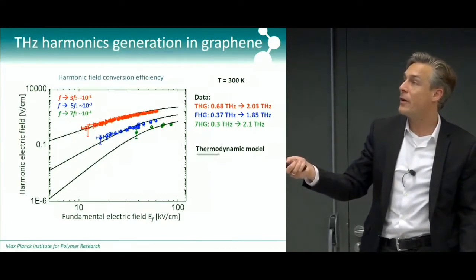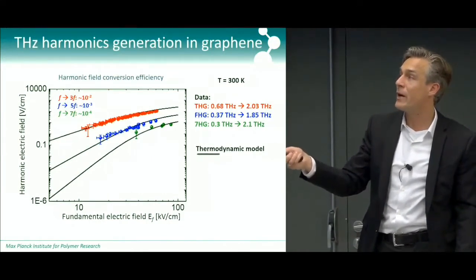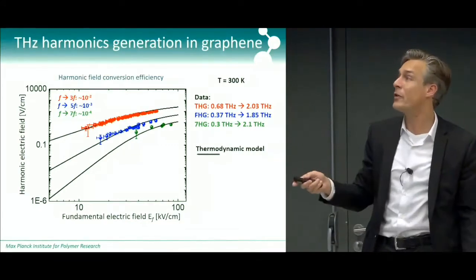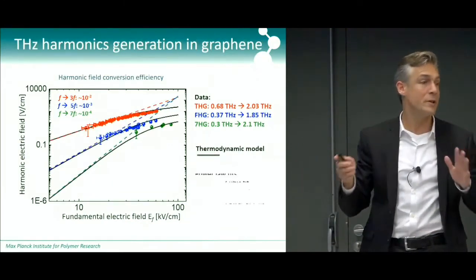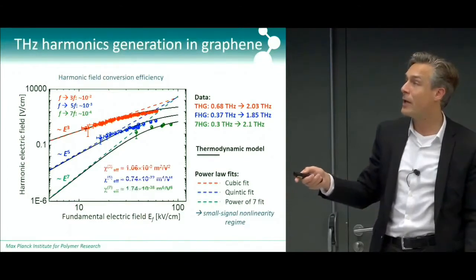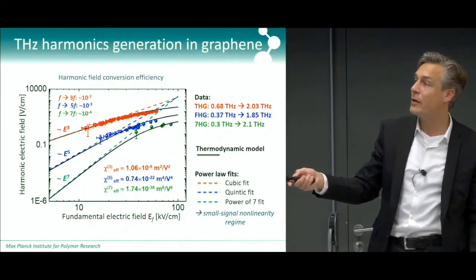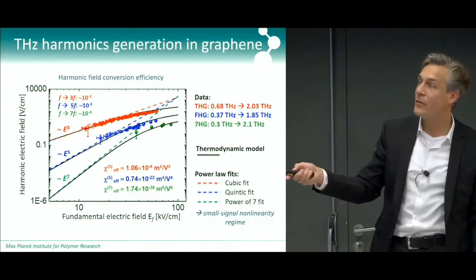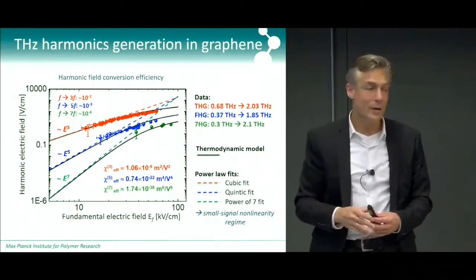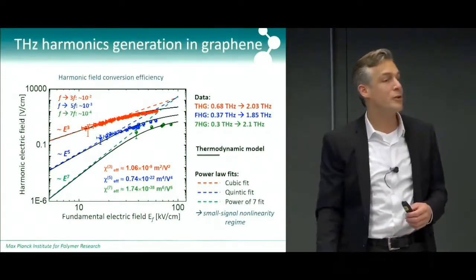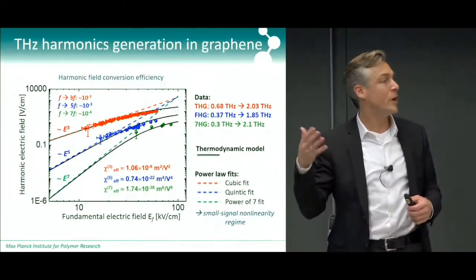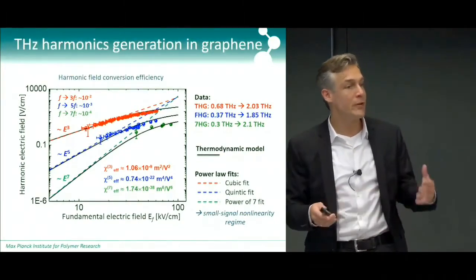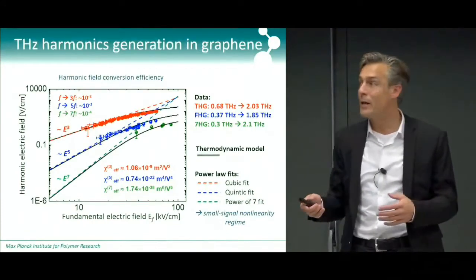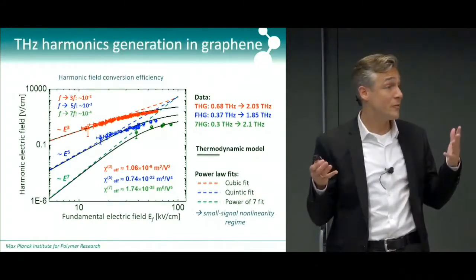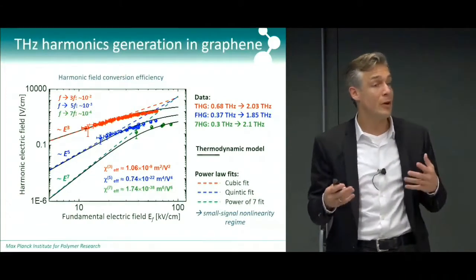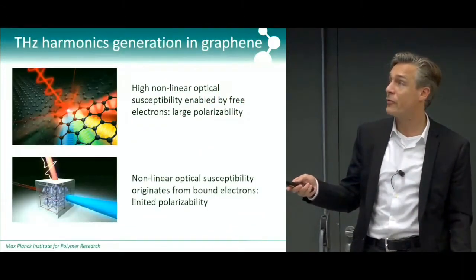And so the lines are again this thermodynamic model. There are no fit parameters in this model, so we know what goes in, we know what goes out. And then you can see that the effective third order, and fifth and seventh order susceptibilities are up to 10 orders of magnitude larger than nonlinear optical crystals that you would use to generate second or third harmonic. And the reason for that is these fundamentally different methods of harmonic generation from these crystals.